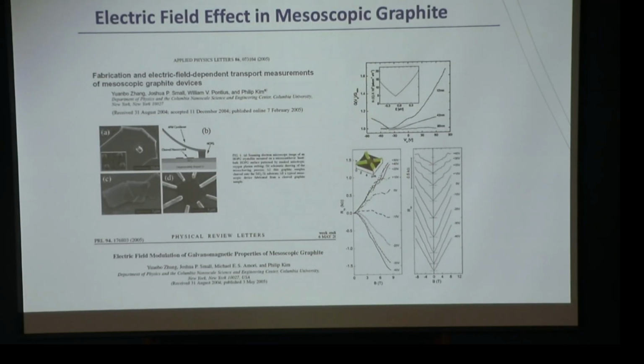Because we started out with bulk crystals, now we get a few nanometers. I think probably about 10 layers of that. We get about 7 orders of magnitude down. We need only 1 order of magnitude down to get to the single layer. This is good, right? Well, you probably know what happens there, right?